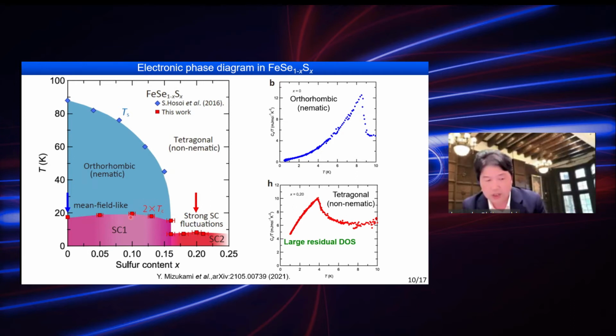In the nematic phase, we have Tc of around 9 or 10 Kelvin. You can see this jump in specific heat. Within the nematic phase, at low temperatures, C over T is roughly linear in temperature, meaning the superconducting gap has a strong anisotropy.